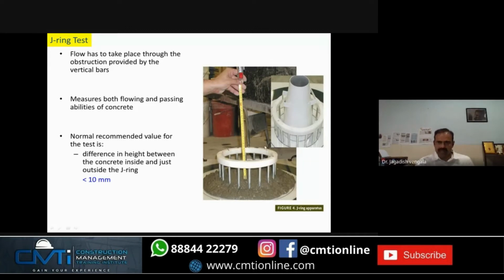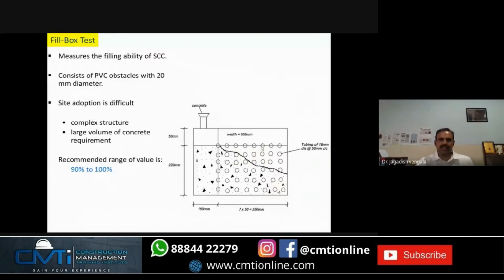So you have a J-ring, and then you place the slump cone, fill the slump cone with self-compacting concrete, lift the cone, and then it has to pass through the J-ring. And you measure the inside height of the concrete and outside height. This should be less than 10 mm.